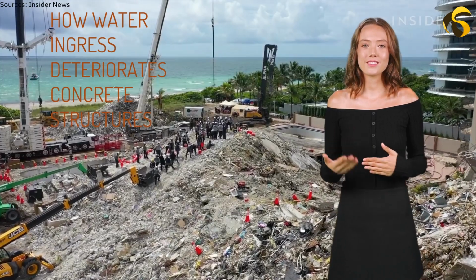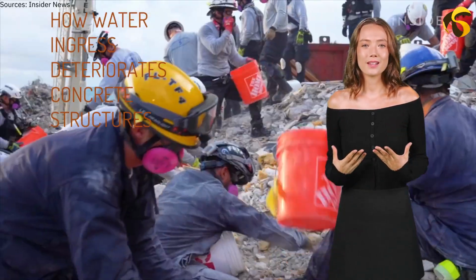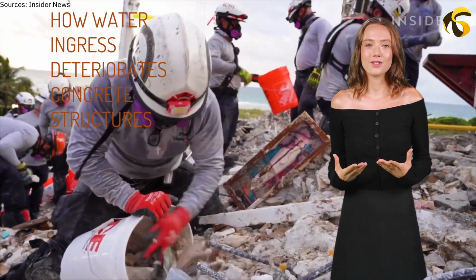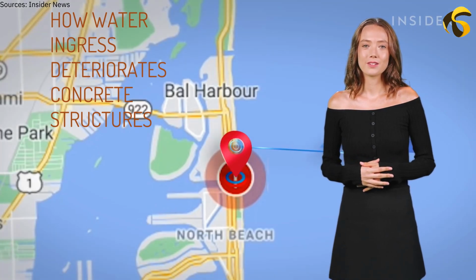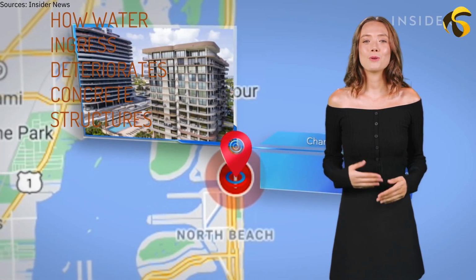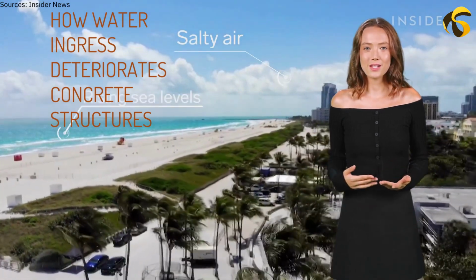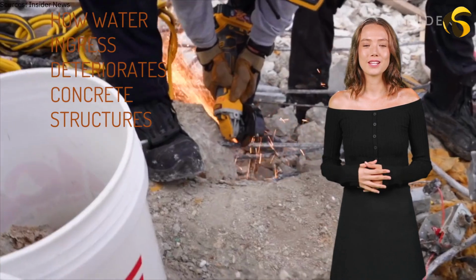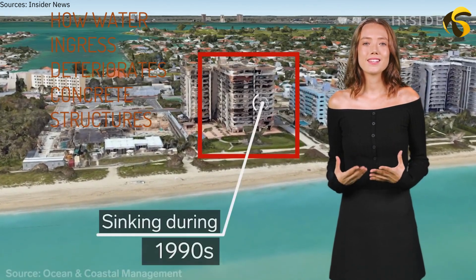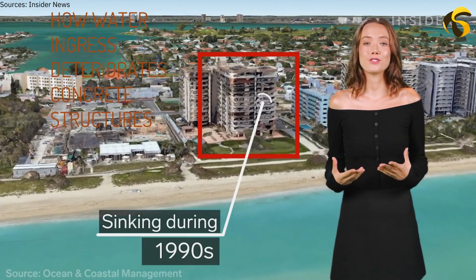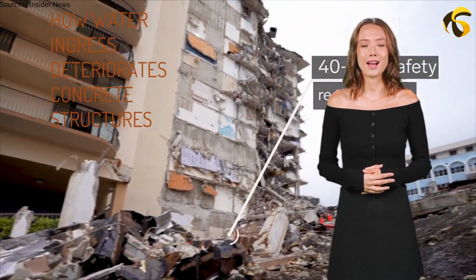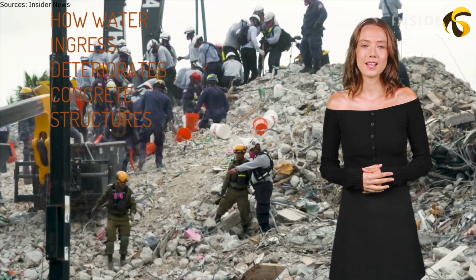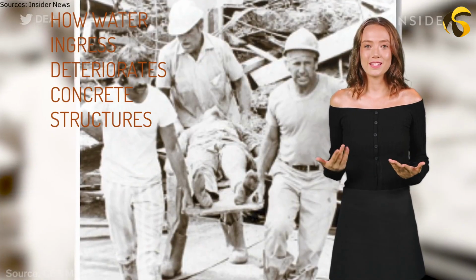Now, if moisture and oxygen are present, the steel will start to oxidize. Rust occupies a greater volume than steel, so it exerts expansive pressure inside the concrete, causing cracking and spalling of the concrete cover. Once cracks form, even more water and CO2 can enter, accelerating the corrosion cycle. Carbonation is generally a slow process, taking decades to reach deep rebar in thick, dense concrete, but it is accelerated by exposure to water, which helps CO2 permeate, and by concrete with high porosity. In Surfside's case, 40 years had passed, enough time for significant carbonation depth, especially in constantly damp concrete.